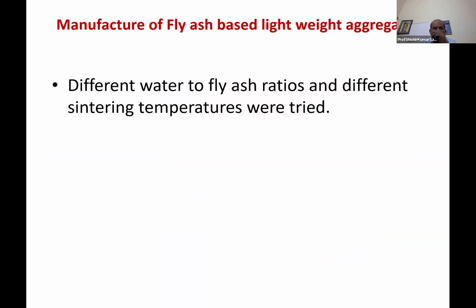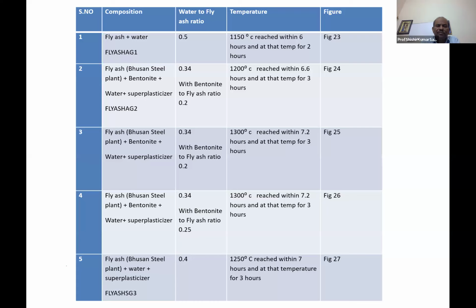Manufacture of fly ash based lightweight aggregates. Here the manufacture is coming. Different water to fly ash ratios and different sintering temperatures we have tried. We have tried many ratios and many temperatures to get good aggregate. Everything gives aggregate, but it depends upon the quality of the aggregate. So these are the trials.